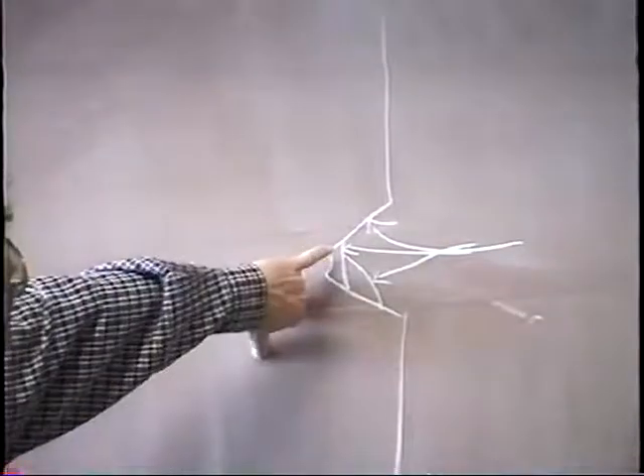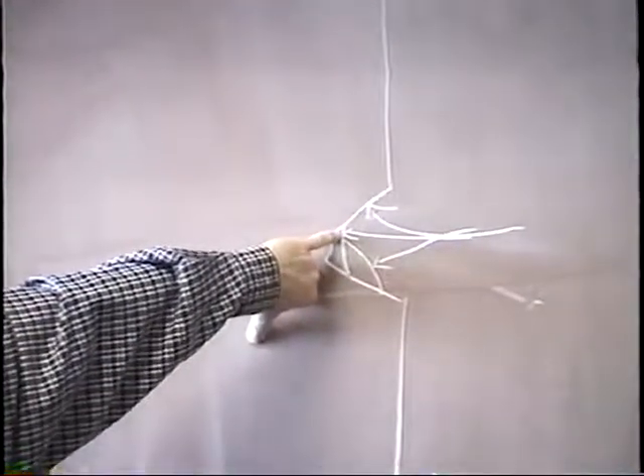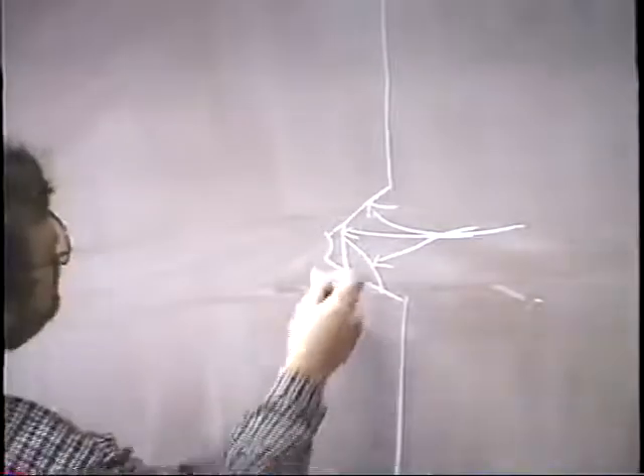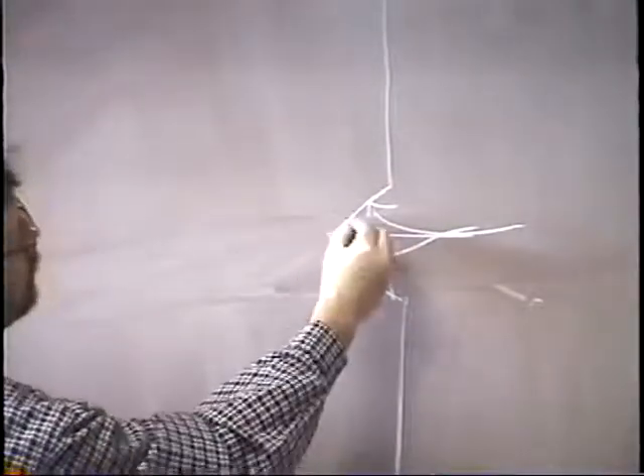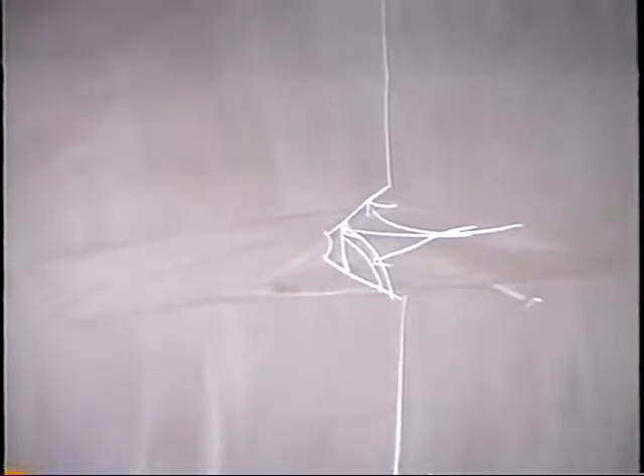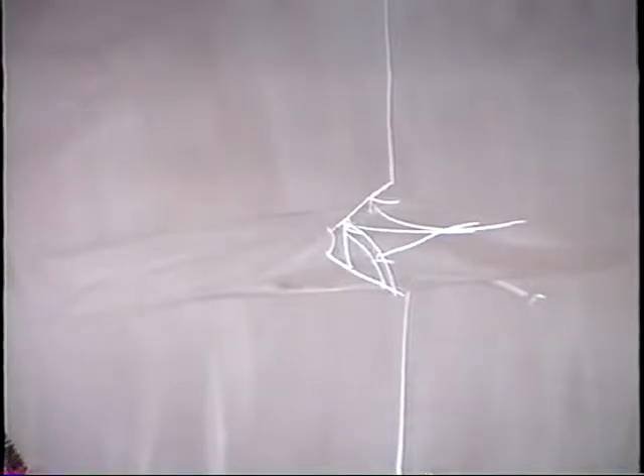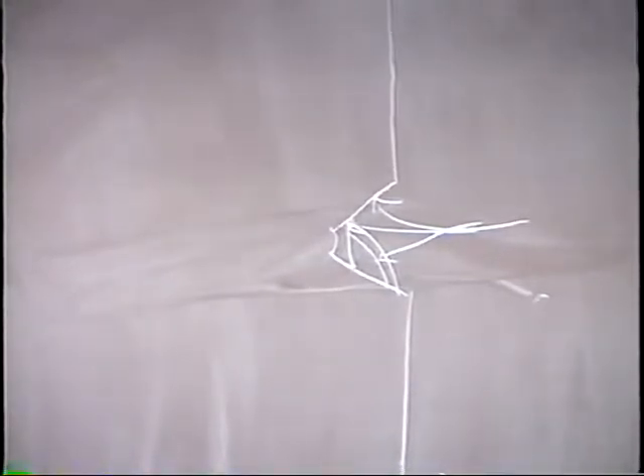Well, to tie into that second pass, you've got to be able to reach it with your welding electrode. If you can't, if you put this pass too high, you could get lack of fusion right up there at the toe of that. When we go to bend it, it could crack on you, or if we were to X-ray it, we could see the lack of fusion, depending on whether or not the X-ray source was correctly oriented. So, an open crevice must be left in which the fourth pass can be deposited, so that you tie into all the surfaces. That's a key phrase you should remember throughout your welding career.